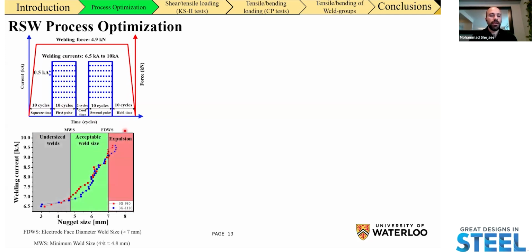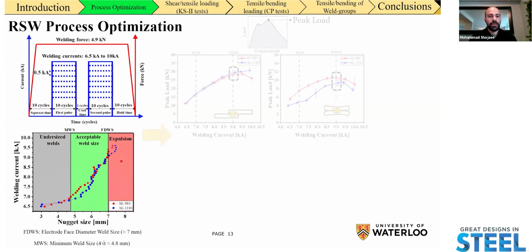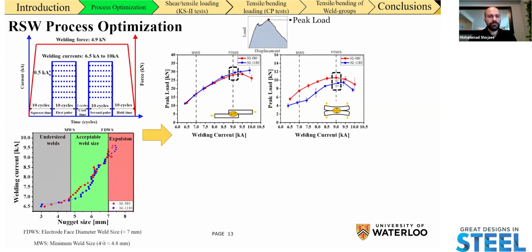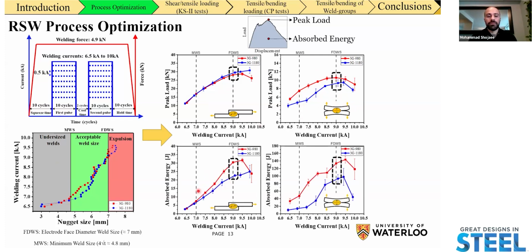and with a 10 cycle hold time. You can see the weldability current range for the two steels at the bottom here, which basically divides the domain into 3 regions where we have unacceptable welds because they're too small, acceptable welds, and the welds that are formed via expulsion. So once we developed this weldability lobe, we performed a standard lap shear and cross tension test. At the top, I'm summarizing the peak load of the lap shear and the cross tension test at different welding currents. At the bottom, I'm showing the amount of energy that was absorbed, which is the area underneath the load displacement curve for these two tests, the lap shear and the cross tension test.